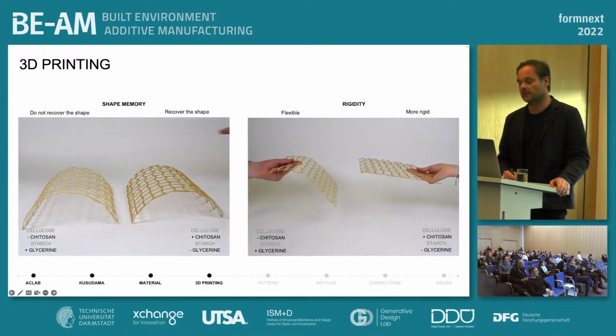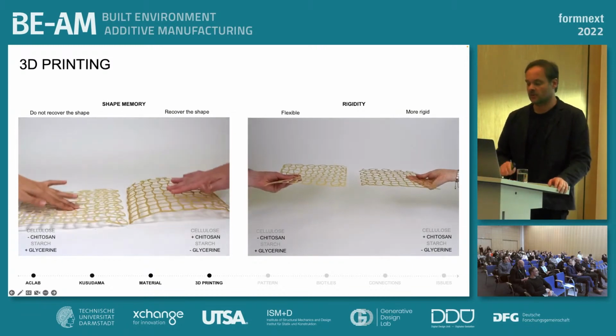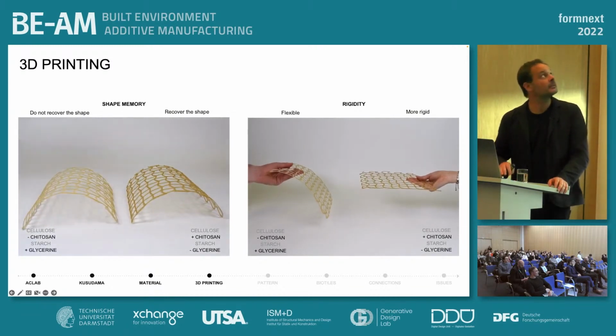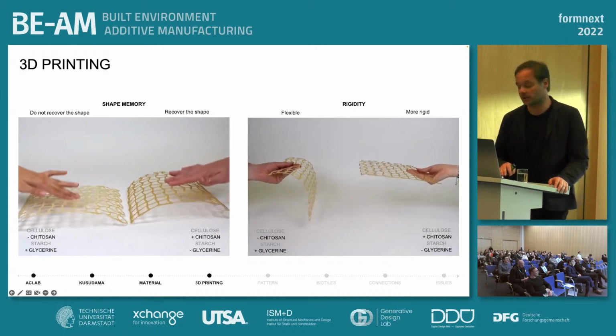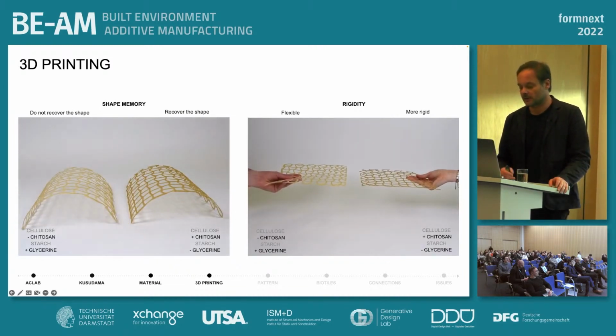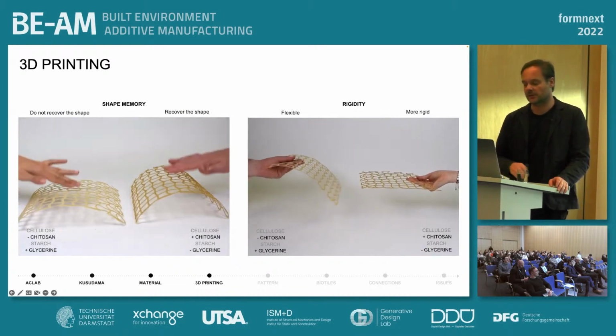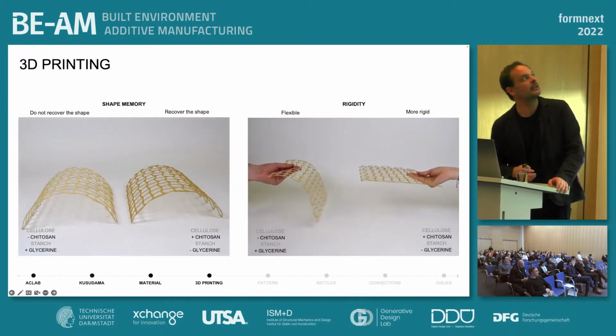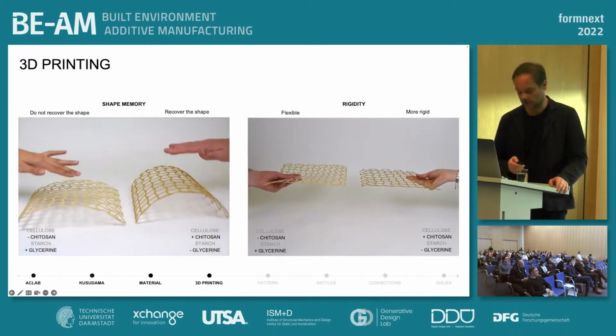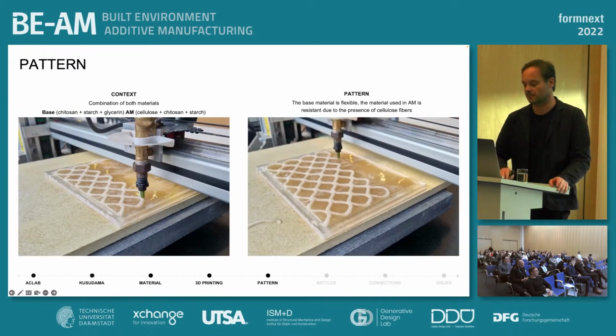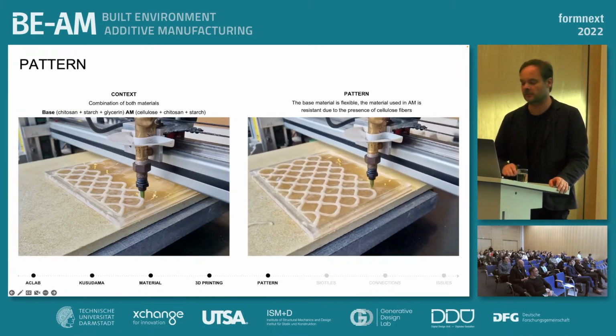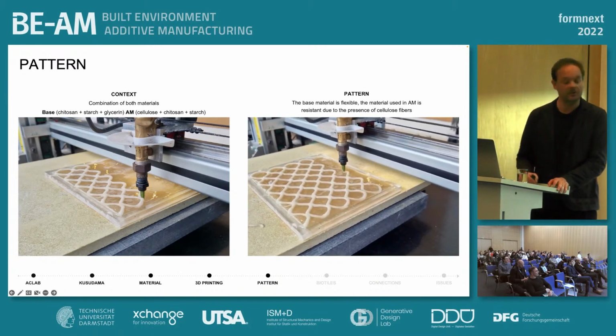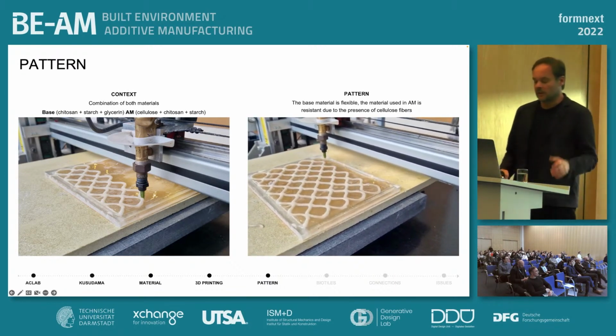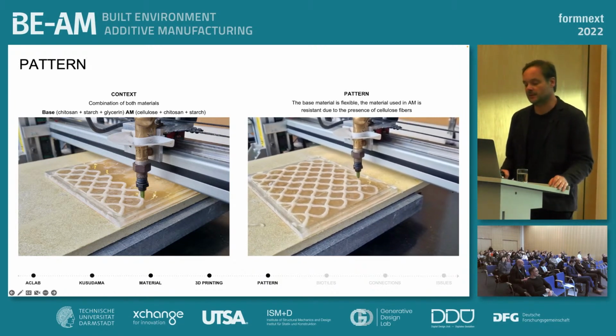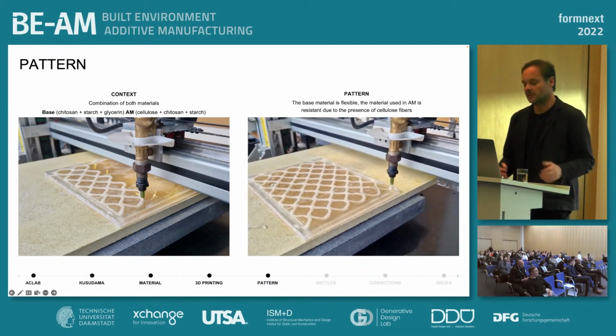When a force is applied on the surface, it changes its shape. The left doesn't recover it, while the right one, with the lower percentage of glycerin and higher percentage of chitosan, more rigid, it deforms, but gets to the initial shape or recovers almost the initial shape. So it's a kind of shape memory effect that you will find in that composition. So we're deciding to mix both materials, a more plastic mixture and a more rigid mixture.